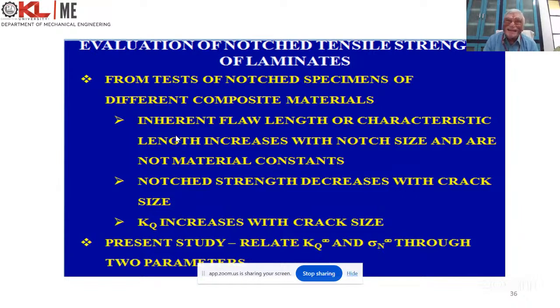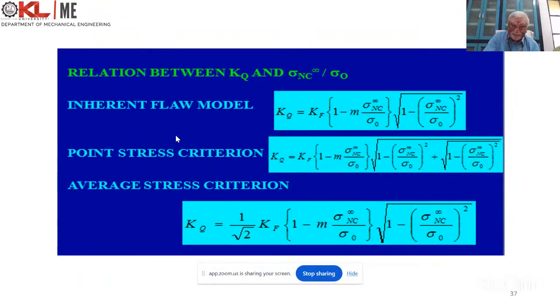This means that for a wide plate, if you are trying to get it for a finite width plate, you can apply the correction factor and translate it, so that each and every time we need not do sophisticated analysis for all the geometries. So these are all the relations between KQ and sigma NC. So that KF and M you can determine with a minimum of 3 tests. One is unnotched strength, another one is 2 different crack sizes. You find out the strength values. From there you can get the values, so that these formulae you can use for estimating the fracture strength of the materials.